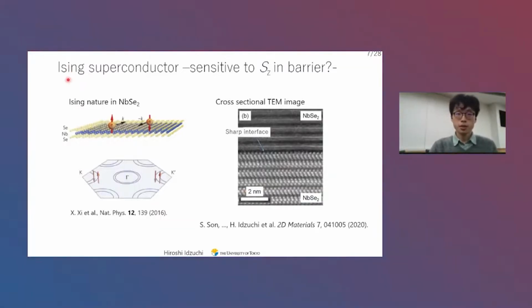Another point of our study is using an Ising superconductor, which is very abundant in the 2D materials family. The most famous is niobium diselenide, where spin is locked perpendicular to the 2D sheets, basically plus D and minus D near the Fermi level. So the spin is really sensitive to this out-of-plane direction. We can imagine chromium germanium tellurides here, and then these Cooper pairs should be sensitive to this CGT's spin. In practice, we also confirmed that we can build a very sharp interface using 2D materials like niobium diselenide. So we can now just insert chromium germanium tellurides here.